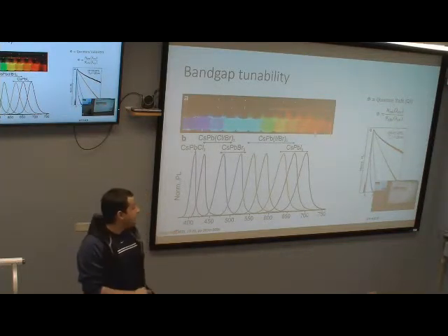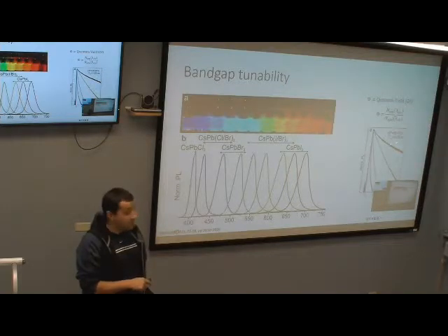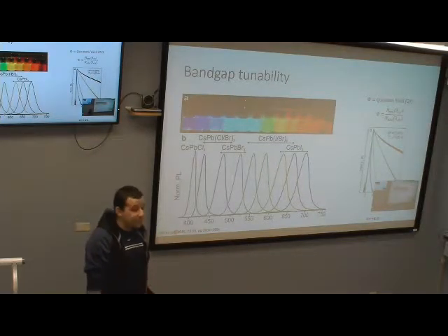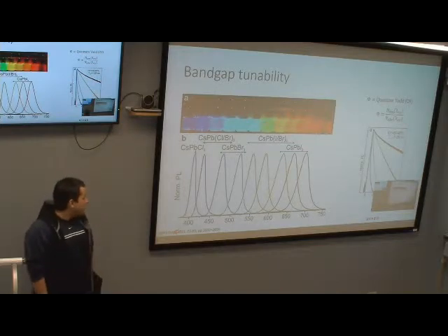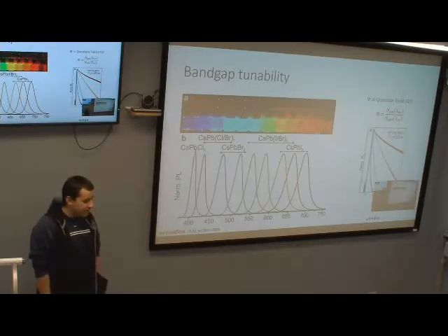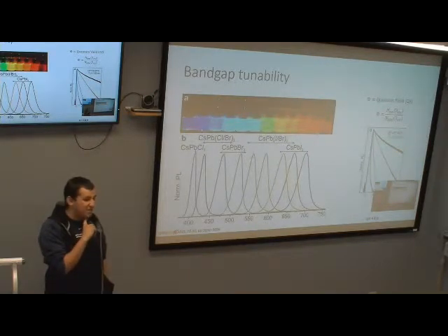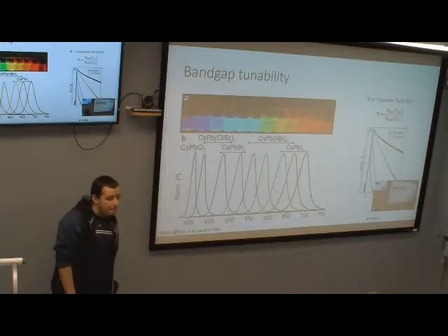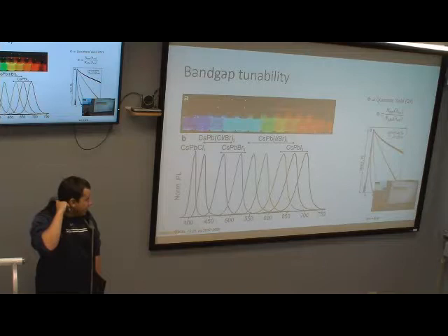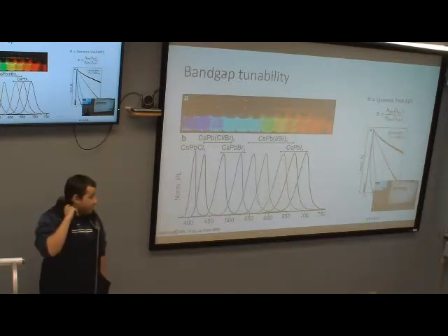Well, yes. The time scale of the relaxation rates happens to be in the nanosecond range, where the iodide solution is found to relax in 29 nanoseconds compared to the blue version, which is found to be a 1 nanosecond relaxation. Chlorine isn't included because they had difficulties with it, but it was probably too fast for the machines to detect. But yeah, I'll look into this a little bit more. I didn't think about it too much.